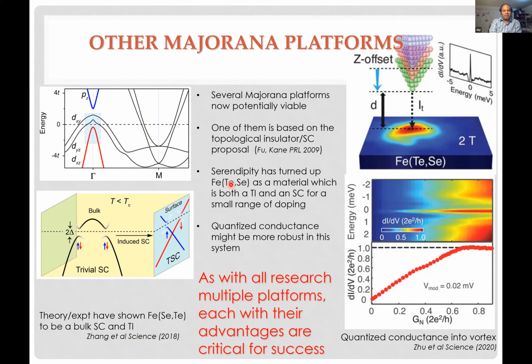Until this magic material showed up, iron, tellurium, selenium superconductors. I mean, the material was around, but what was realized is that for a small range of doping, this material could be a topological insulator in the bulk. And indeed, then you have a situation where you have a surface state of a topological insulator and a bulk superconductor from the same material.